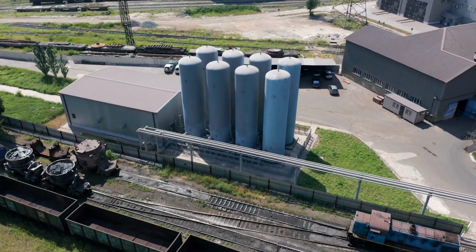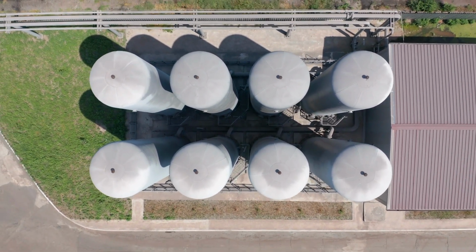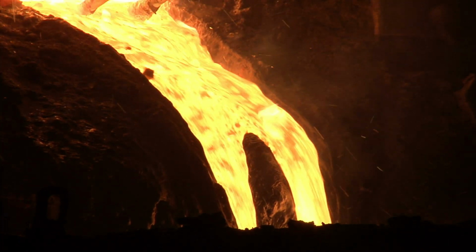What we're seeing happening with steel companies' plans for the transition towards green steel is very much focusing on the utilisation of existing technology. This is what we're seeing in Europe, who are the leaders in the transition at this stage. Most of the plans there revolve around the partial replacement of blast furnaces with DRI technology. Initially, these will mostly use natural gas, which, despite sounding bad, actually still results in a decrease in carbon emissions of up to 50% compared to traditional blast furnace steelmaking.